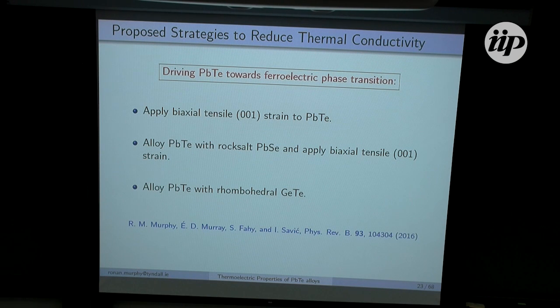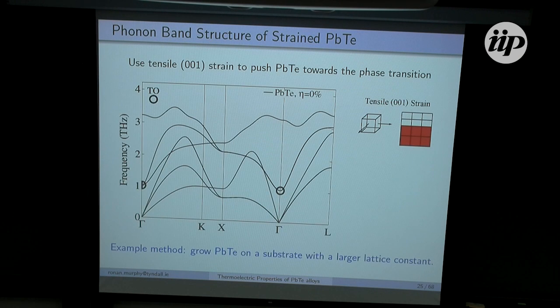And I'll get back to that later. So first off, I'll just talk a bit about applying biaxial tensile 001 strain to lead telluride. To start off with, again, I have the phonon band structure of lead telluride. I've highlighted, again, the TO mode at the gamma point with this black circle. It's at a frequency of about 4 terahertz.